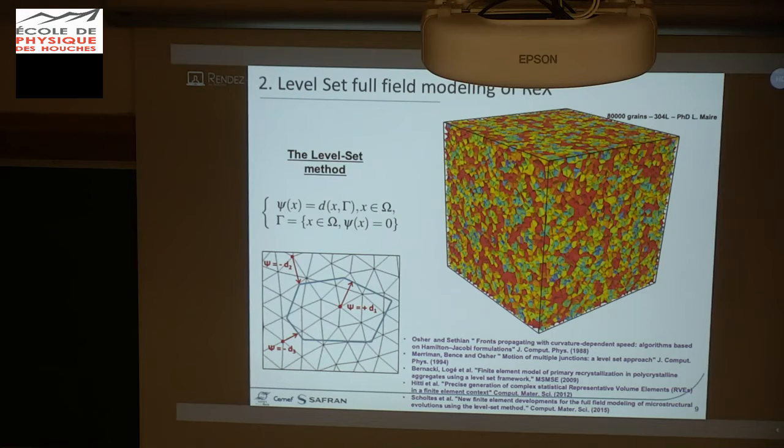And you can generalize this methodology to an important number of grains, as you can see in the picture on the right side, where you have a stainless steel polycrystal with 80,000 grains, realized by Ludovic Maire during his PhD. Of course, we also use coloring algorithms, coloring theory, to minimize the number of level set functions needed to describe such a polycrystal in a finite element mesh. Typically here, you have only 30 level set functions to describe this polycrystal. The main aspect is that you can use one level set function to describe a large number of non-neighboring grains.